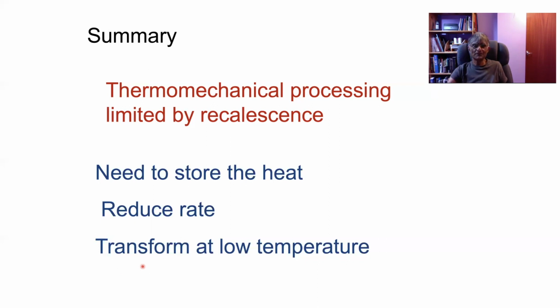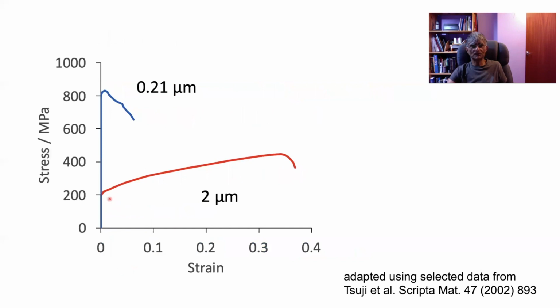There's one more problem. Okay, so these are experiments reported on interstitial free iron, where if you look at a grain size of 2 micrometers, we have a strength level there, but lots and lots of elongation. But if you decrease the grain size by an order of magnitude, it's not nanostructure, that is small, you get a rapid plastic instability. So there's almost no uniform elongation. Now, the reason for this is when you make the grain size small, the defects sink into the grain boundaries. Once that happens, there's no work hardening mechanism, and therefore you get rapid plastic instability.